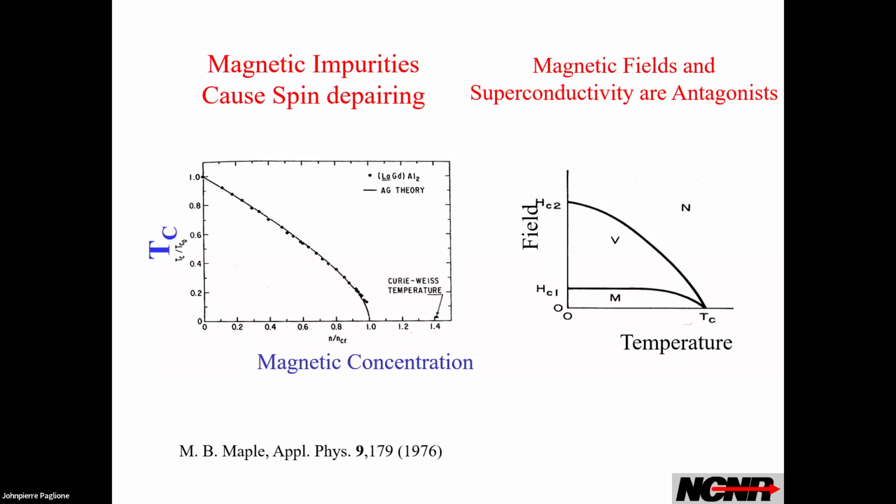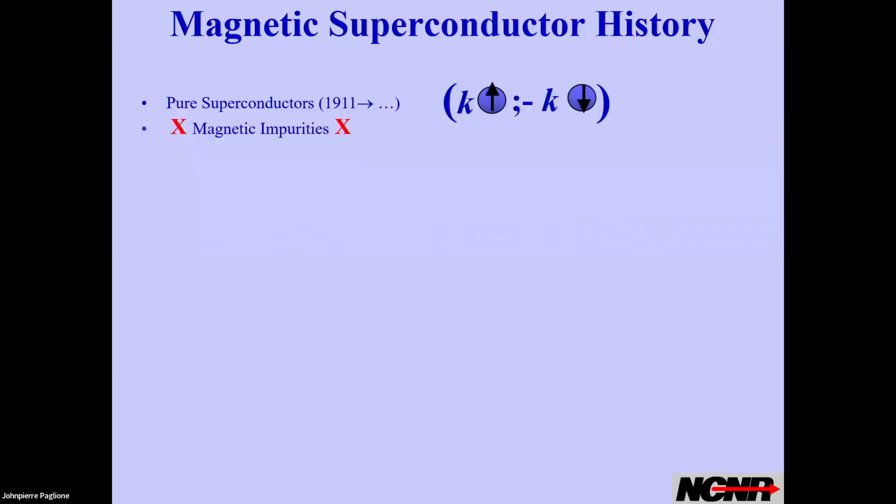The other thing about conventional superconductors is that if you try to put magnetic ions in, it breaks up the superconductivity very quickly. All the conventional superconductors follow almost, there are always some exceptions, which I'll talk about in a minute, a kind of universal curve developed by Abrikosov and Gorkov. And typically this critical concentration is maybe 1 or 2%. So there's almost no chance to get collective effects. So that's the standard thing.